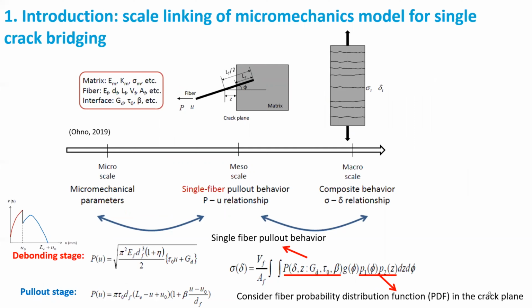And also a very brief introduction of the micromechanical model we're using. We use the micromechanical parameters to build up the single fiber pull-out behavior, which depicts one fiber bridging one single crack. Then we use the fiber distribution function at the crack plane to scale up to the composite behavior and come up with the sigma-delta relationship as the output. From this sigma-delta relationship, we can calculate the maximum complementary energy and the crack bridging stress. These values could be further used for calculation of the PSH indices to evaluate the strain hardening potential of the mixture.